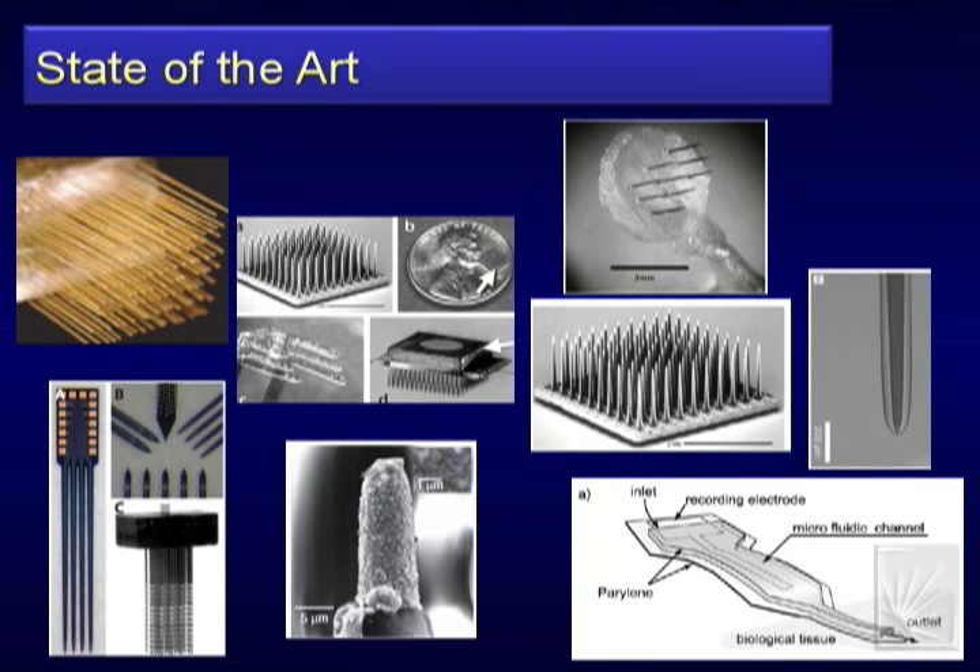It's hard to have a 20-year solution because drug will disappear in current models. One approach is having a conduit of not just electrical but also fluidic information — different interfaces, different coatings like PEDOT and polymer coatings for charge density reasons. And there's the idea of addressing mechanical mismatch between brain and probes. People are looking at polyimide and different structures trying to create devices that are much softer — closer to brain modulus than silicon probes.